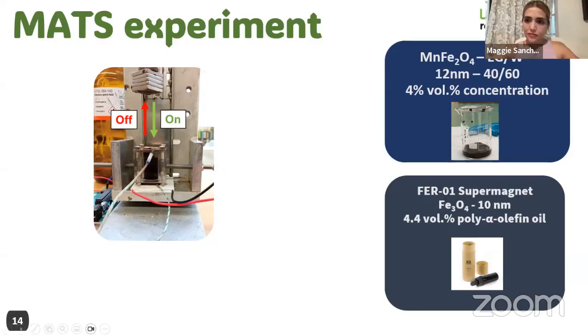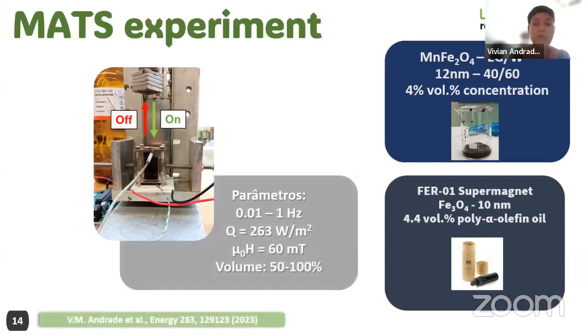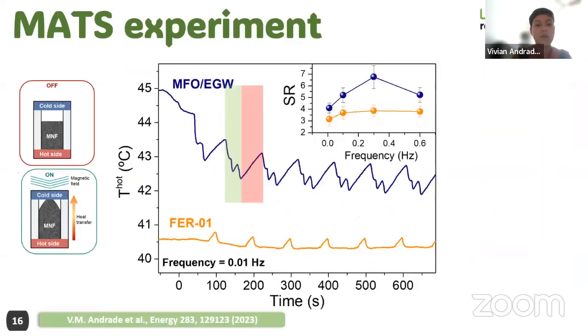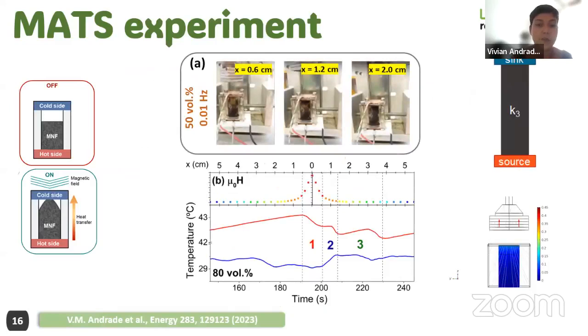We have here a higher saturation magnetization, but Fe3O4 also has a very strong saturation magnetization at room temperature. So what we believe—we haven't performed this study yet, but we believe it's mainly because of the viscosity. The viscosity is playing a role, and since we have a lower viscosity here, we have changes in the effective thermal conductivity. If you look here, with 0.6 centimeter, the material starts to go to the heat sink.